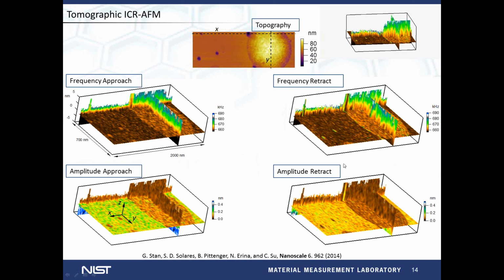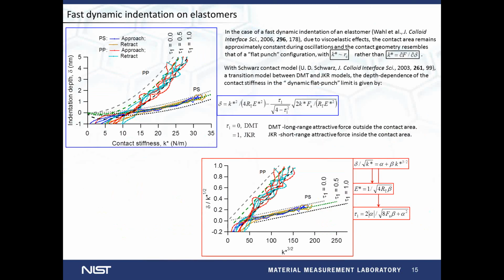A closer look at the color contrast, for example, at the zero indentation planes, reveals differences between the dynamics of contact formation and contact breaking on each material and between the two materials. That gives us more information about contact formation and contact breaking, right? We can convert this into a three-dimensional representation of contact stiffness and dissipation, but we would like to talk next about a detailed analysis of the depth dependence of the contact stiffness and dissipation.